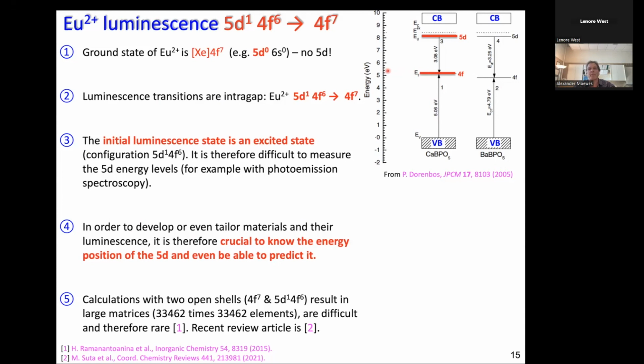Now, because the dopant is put into a host lattice, it turns out that these states are what's called intra-gap. So there is a band gap between the valence band and the conduction band. And it turns out that these additional states from the dopant that are responsible for the visible light output reside in the band gap. And when you know that europium 2+ has no 5D electrons in the ground state, so it has 5D0, then you will see immediately that it will be difficult, because it basically requires a two-photon experiment. It will be difficult to probe the exact position of the 5D orbitals.